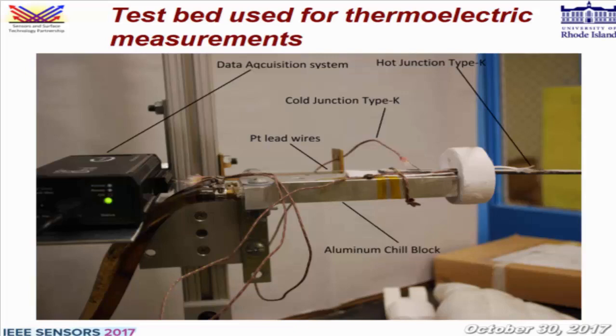We put the free floating end in a tube furnace, and that thermal gradient from hot to cold is actually the driving force that produces the thermoelectric potential. We have two type K thermocouples measuring the hot temperature and the cold temperature, and the sensor itself has platinum wires which extend out to a DAQ system, and we get voltage readouts from the sensor.